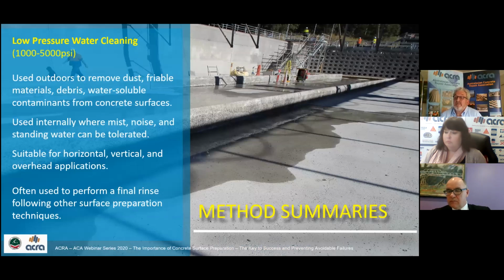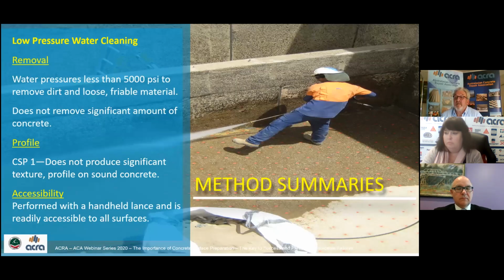Let's look at low pressure water cleaning. Low pressure water cleaning is used to remove dust, friable material, debris and water-soluble contaminants. It's used in interior spaces, for horizontal surfaces, and also as a final rinse on other surface preparation methods. Water sprayed at pressures less than 5,000 psi doesn't remove any significant amount of concrete. Profile gives us CSP1, and accessibility.